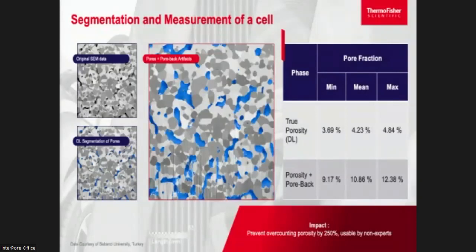This is in scanning electron microscope images returned not only for the face of the specimen but also for the back of the pores. Traditional image processing capabilities such as thresholding, watershed, and top-hat tool will show the true porosity but as well the presence of pore-backed artifacts. This would cause inaccuracies in the estimation of porosity. So using deep learning capabilities, it is possible to measure the actual porosity and to train a model that would predict this or to detect artifacts in the sample.